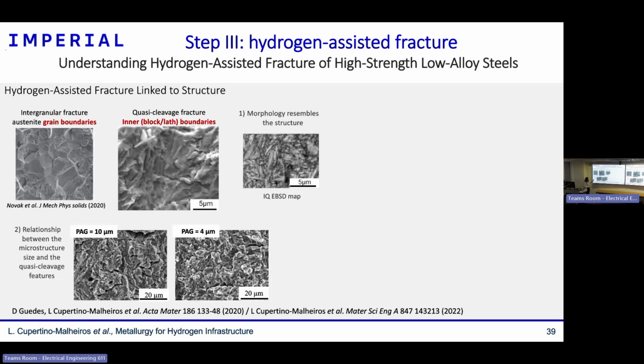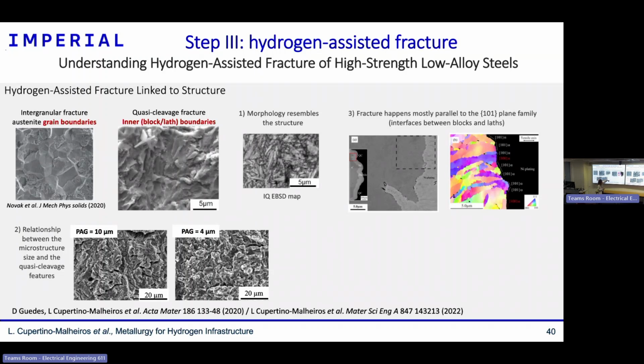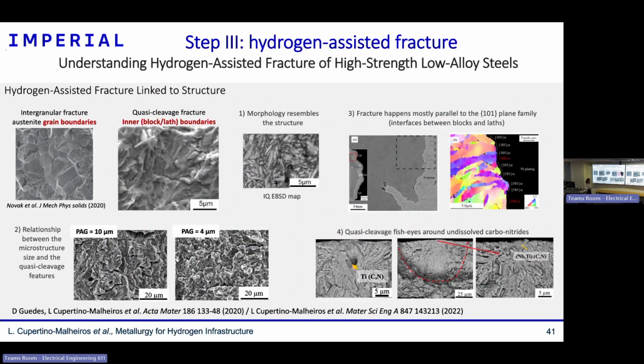Another indication I saw is that the size of the quasi-cleavage features is related to the size of the microstructure, with larger microstructure having larger quasi-cleavage features. And finally, I did EBSD at the fracture surface, and I saw that the fracture happens mostly parallel to the 101 planar family, which is also the interface between some of these inner boundaries of martensite. So all of that indicates that these inner interfaces are cracking with hydrogen. Another feature that I often saw related to hydrogen embrittlement were some undissolved big carbonitrides that can come with the process and should be avoided.